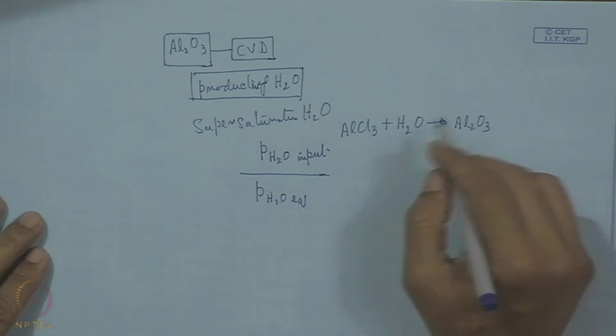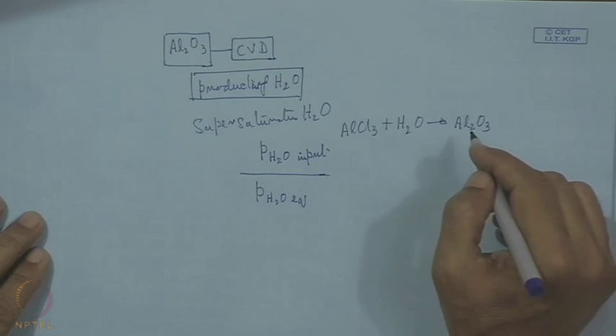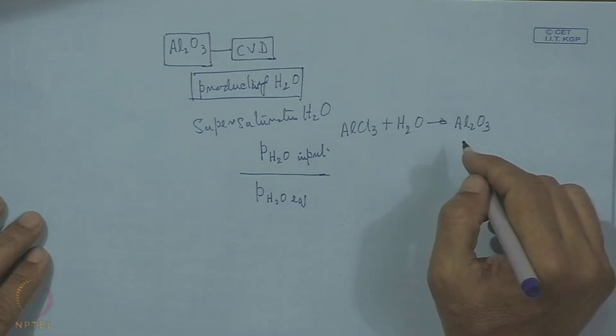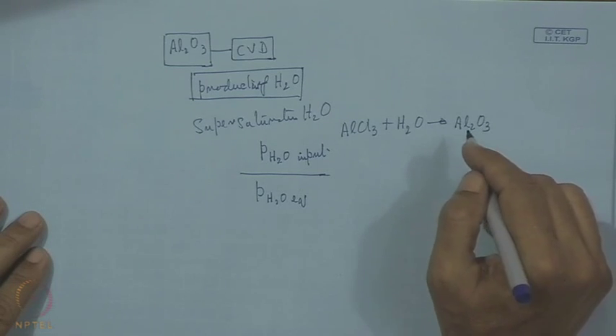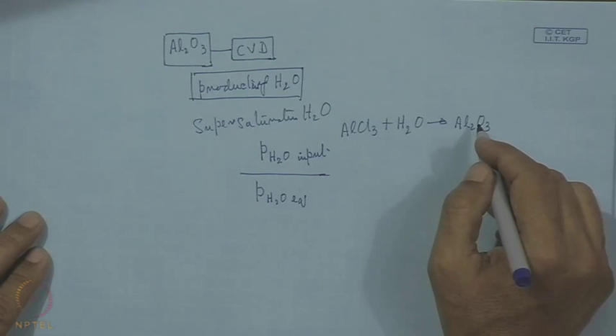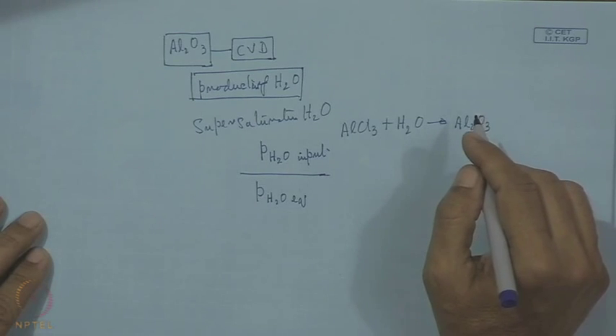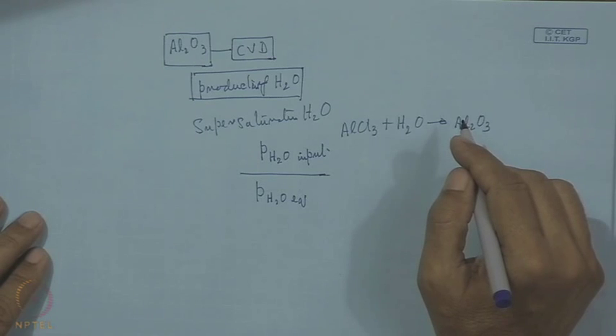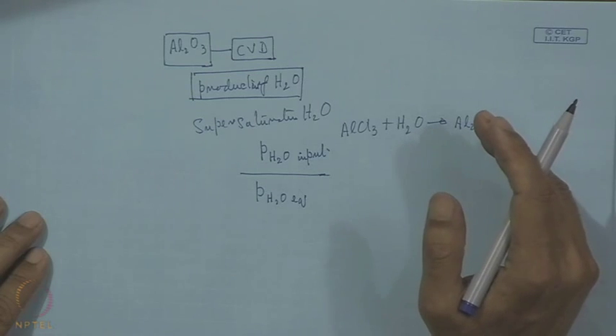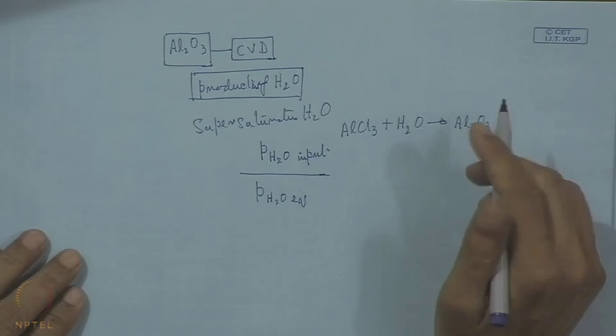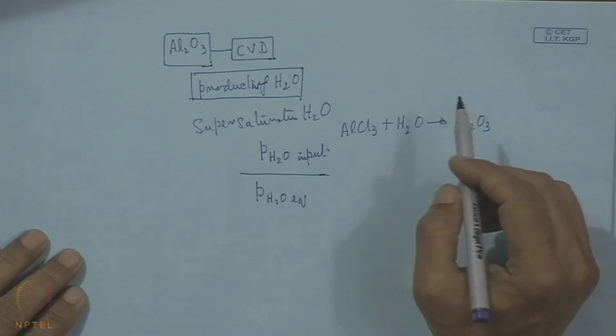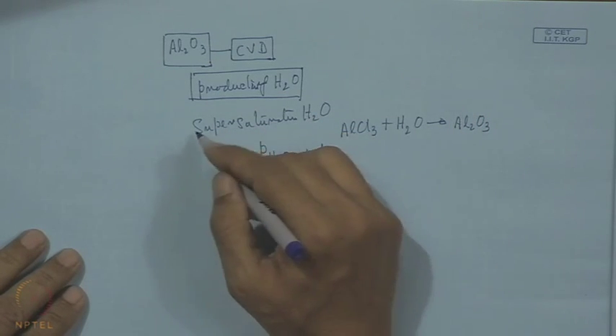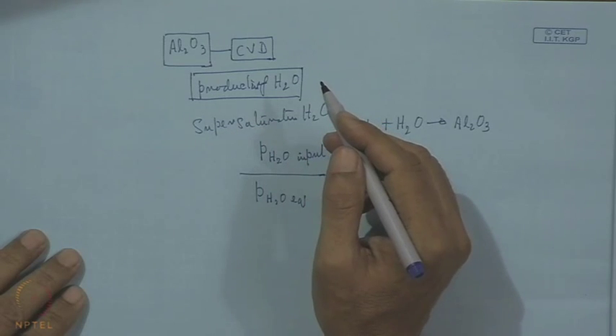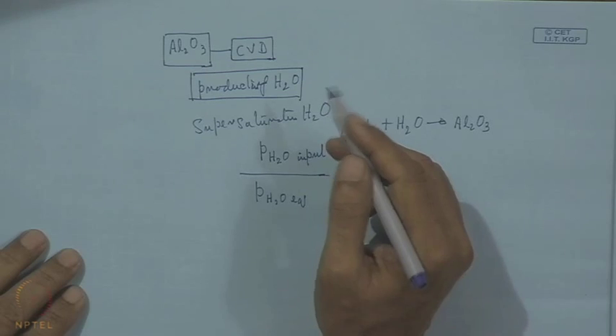So, if we move this reaction at a very fast rate, then we can have rapid growth of this Al2O3, and in that case the nucleation rate will also be quite high, and as a result we may expect a finer grain size and a smoother coating on this carbide tool substrate. So, in principle one should attempt to make this supersaturation of H2O as high as possible.